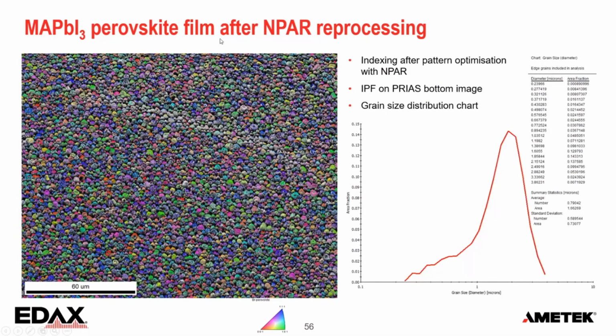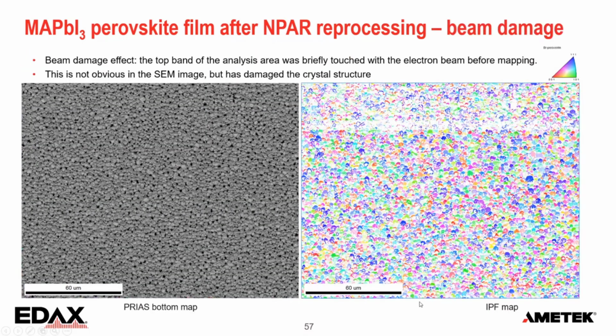Now, going back to the map, of course, I can do a grain size, I can do misorientations, I can do all the normal EBSD analysis. And then I tried another one. And this was on a sample where I had collected a few of the images I've shown in the beginning. And here, I just have an area, the top 20% of the map, where the indexing is clearly much worse than further down. And this is the effect of a single beam pass on the sample. So that's the level of sensitivity.